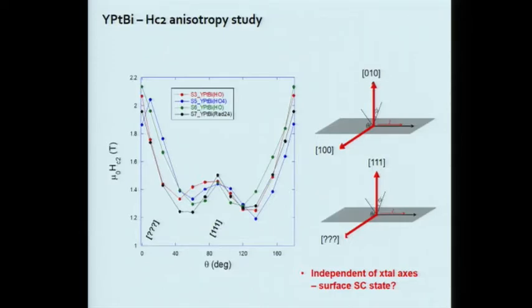But we're doing some experiments to actually test that, because it's a bit strange to me that if you have current voltage leads on a crystal that are on this side, it doesn't pick up anything that's on this side. It should be something, but maybe not. So this is 4 different samples that are showing the same behavior, and it seems to be geometry dependent. So another experiment to do next is to use some maybe square cross section, or as close to cylindrical as we can, and then try to rotate and see if there's any change there.